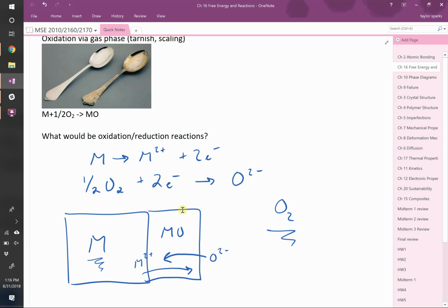But if you grow from 1 mole of metal, 1 mole of oxide and it's a lot bigger in volume because of the way that the atoms arrange themselves, which we'll learn in a couple chapters, then all of a sudden this thing's really big. Imagine it's going to be experiencing a compressive force. If it's trying to expand but its substrate doesn't let it, then it's eventually going to chip off, right? That's what happens with rust. It chips off, like iron oxide rust.